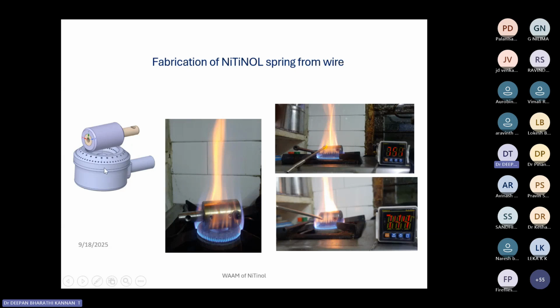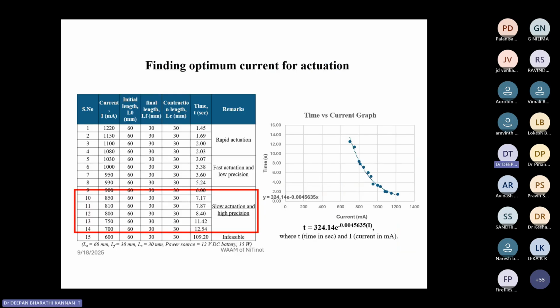So here they were using a fixture for converting the wire into the form of springs. Whatever they have done in the previous video, the students purchased nitinol wire and were able to convert it into a spring and set it as the initial shape. As we have seen in the first couple of slides, they were able to change the initial shape to a spring by heating to a temperature of 750 degrees Celsius and maintaining it there for some time. They were also studying the effect of chemical composition on the shape shifting, and they are currently working on that also. So what they found from their work is the effect of current on the actuation.